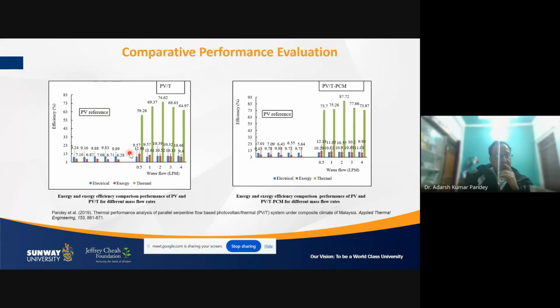Okay, you see that this is the PV as a reference. With PV as a reference, you will find the electrical efficiency was close to a maximum of 9.89%, and you do not have any thermal energy. But when you attach the thermal collector into it, the maximum efficiency goes as high as roughly 10.39%, and further, on top of that, you get the thermal output out of the same system. You do not need another area. With the same area, you can get the thermal output as well as the enhanced electrical energy.